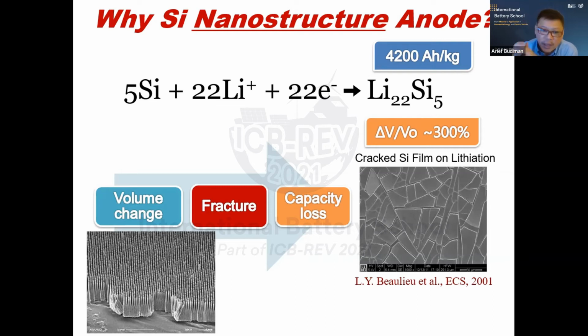And obviously, in the current form of thin film, so that's what I'm showing here, this is the only current form available in the technology for 100% silicon. Obviously, this is not the right form because you can see it cracks. It absorbs the lithium ion very quickly, and because of that it expands quickly, and because of that it cracks, it breaks basically.